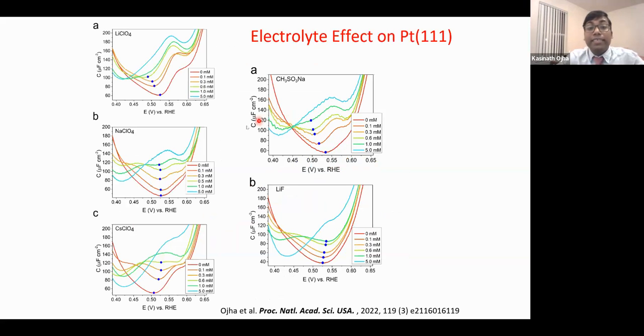What we see is that in different ions, the minimum in the capacitance curve changes direction. If you have a smaller cation, let's say lithium ion, then your minimum shifts to lower potential. If you have a bigger ion, cesium ion, then it shifts to higher potential. In the same way, with bigger anions it shifts to lower potential, and with smaller cations or smaller anions it shifts to higher potential. So some kind of effect is there, that the ion is interacting with the surface. We believe that interaction happens through the water structure on the surface, and that leads to some kind of additional capacitor, which gives really high capacitance in the double layer structure. That's why we are getting much higher capacitance than theoretical expectations.